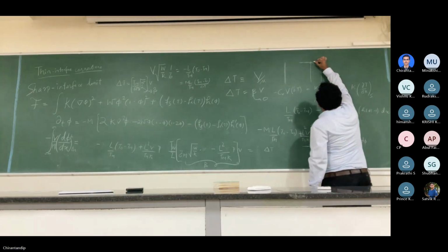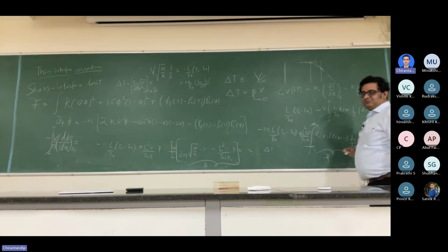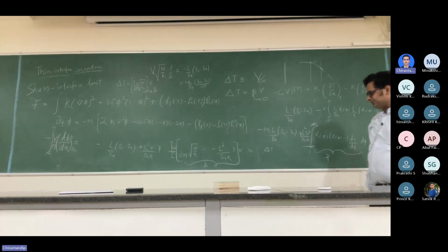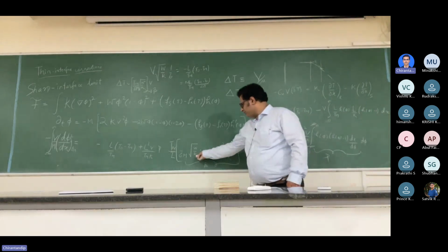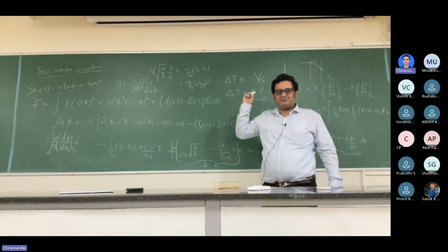Essentially, if I take this value, that is Tn, that means T naught minus Tn is 0. And that is ensured if you choose your epsilon, K and W in a way that this term vanishes.